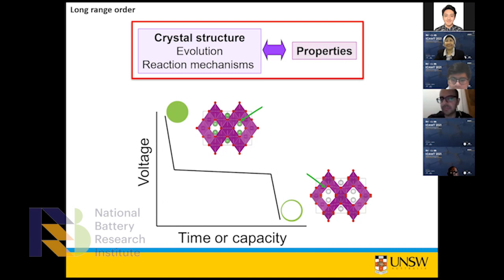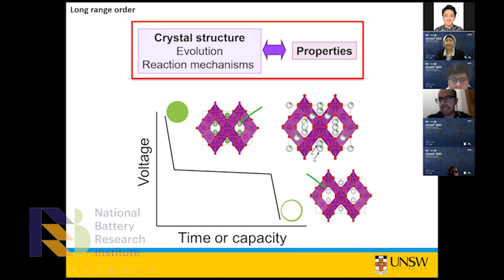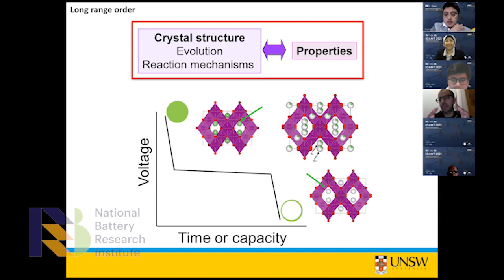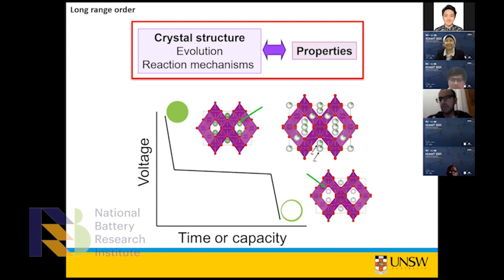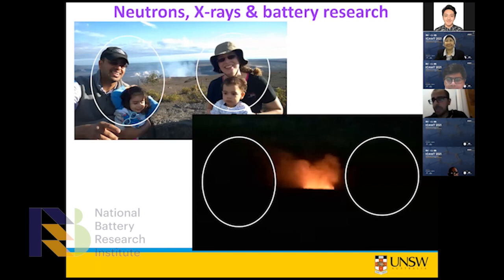You might say these are the two channels I'm looking at — if I make them bigger or have them hold more lithium, I could increase capacity or change the rate. But looking at a pattern somewhere in the middle, you realize it's not just one site coming in and out; there's actually a lithium pathway, and you have to tune your structure to optimize that pathway. You might also want to look at dynamics to see how that pathway evolves. Having this atomic-scale picture of a material, ideally in a device, is fantastic to understand what's happening and then to build better devices.